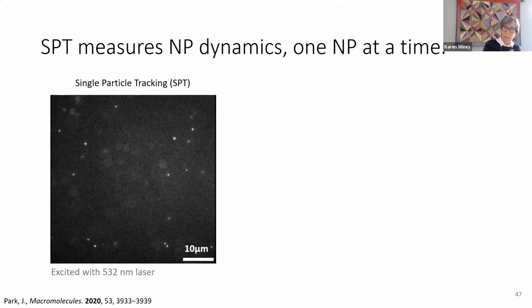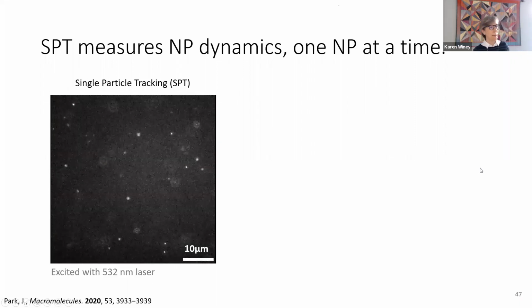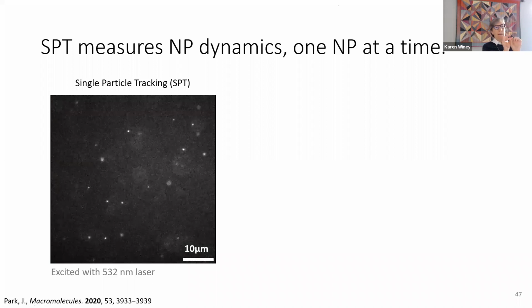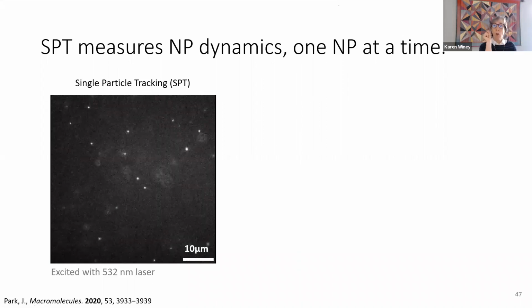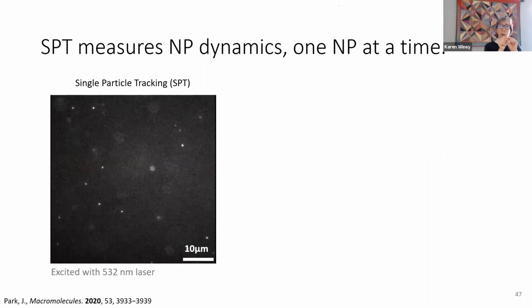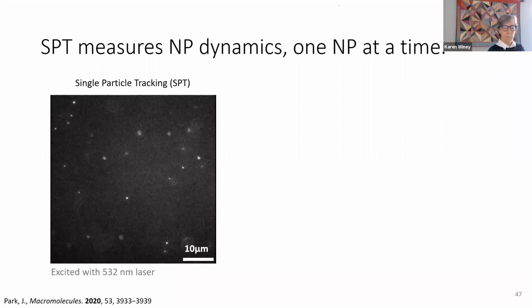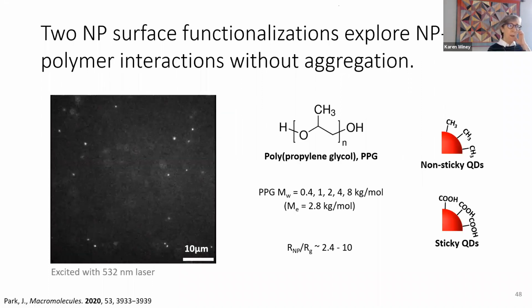And in the melt state, single particle tracking is, we're using quantum dots. There's a lot of math involved to find the center of those bright spots, and those bright spots are larger than the particle, but we can still very precisely determine the center of those particles as a function of time. The chemistry we're looking at here, and what we were really excited to do, was to look at both sticky and non-sticky quantum dots. Again, the sticky ones will have a polymer adsorbed and that will prevent agglomeration, but for the non-sticky ones, there's really no other way to do this experiment with non-sticky particles to get their diffusion.